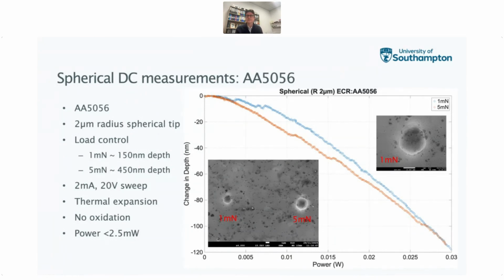And so from that point of view, we decided to switch to a spherical indenter tip to see if we could achieve something where we're really lowering the contact load, as the metrology necessarily demands. So we used a 2 micron radius tip in this instance with the aluminium alloy. And again, we've done a couple of indents with 1 millinewton and 5 millinewtons, about 150 nanometers depth and 450, as you can see here.